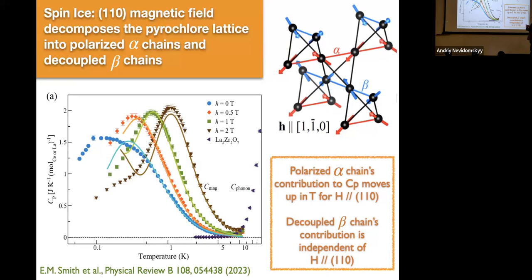And then as you crank up the field, we're not cranking it up very high, only to 2 Tesla, but what happens is that the magnetic heat capacity splits into 2 pieces. One piece sharpens and moves up in temperature, and the other piece is unaffected. The piece that sharpens and moves up in temperature is due to the polarized alpha chains. The piece that doesn't change at all is due to the beta chains, because the beta chains are unaffected. So again, this behaves exactly as we expect the spin ice to behave. Okay. So that's where I'm going to end the story now.